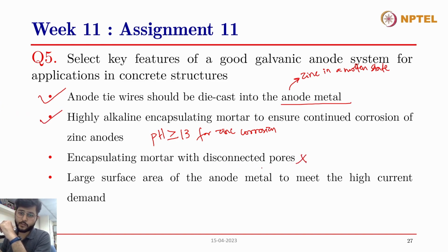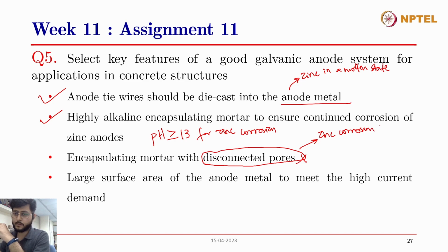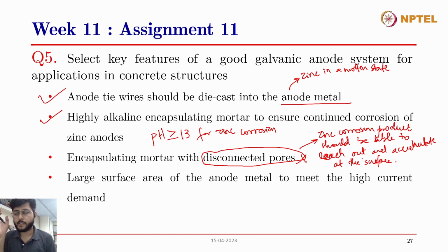Encapsulating mortar with disconnected pores? No, we do not want disconnected pores, because when the zinc corrosion products are formed, they should be able to leach out and accumulate at the surface. If they get accumulated inside the galvanic anode system, then since these corrosion products are expansive in nature, they'll expand the volume, and that will create expansive stresses inside the cementitious mortar, and that will create cracking of these galvanic anode systems, and it will get destroyed within a few years.